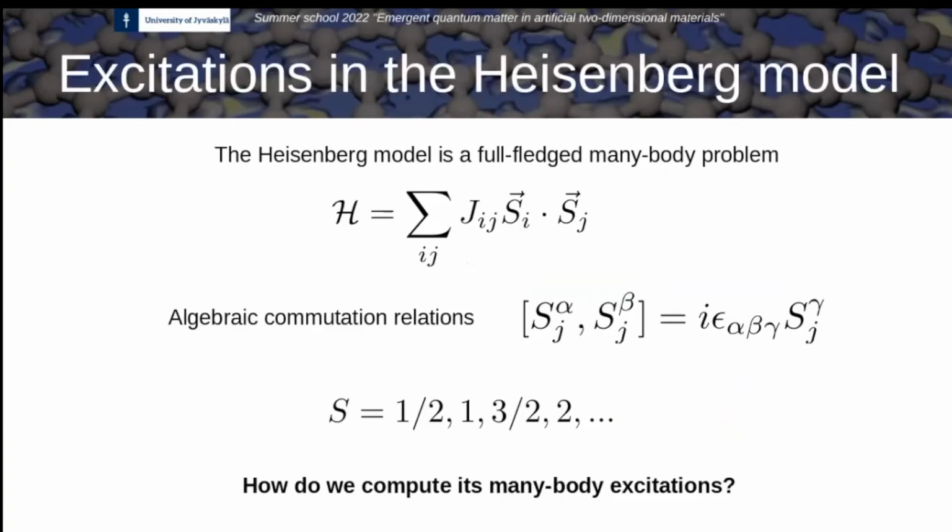So now we are going to see how to derive a Hamiltonian for magnons, starting from the Heisenberg model for a two-dimensional van der Waals magnet. So we will start with a Hamiltonian like this. It can be ferromagnetic, it can be antiferromagnetic. Let's take it ferromagnetic for concreteness. And we are going to assume that on each site we have a spin. And the spin can be 1/2, 3/2, 5/2, and so forth, depending on the filling of the d orbital that we have in our manifold. For example, for several 2D magnets, such as chromium iodide, chromium bromide, chromium chloride, the relevant case is spin 3/2.